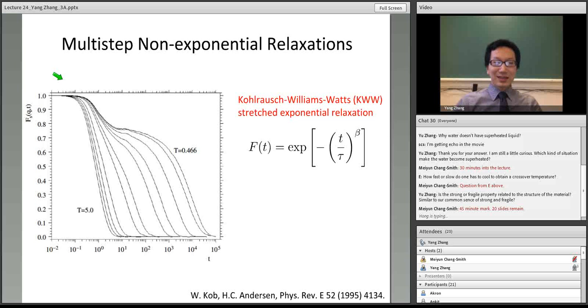So the next striking behavior of supercooled liquids and the glass transition is the so-called multi-step non-exponential relaxation. This figure plots the self-intermediate scattering function Fs(Q,t), which can be measured from incoherent neutron scattering experiments. We usually plot that in a log scale because at low temperature, it takes a very long time for this intermediate scattering function to decay to zero. At high temperatures, you can see the relaxation behavior is very simple. It's a simple exponential, a so-called Debye-like relaxation.